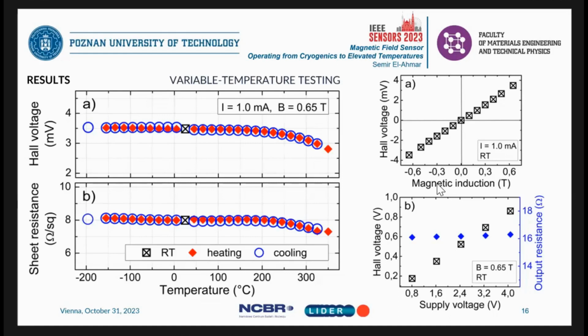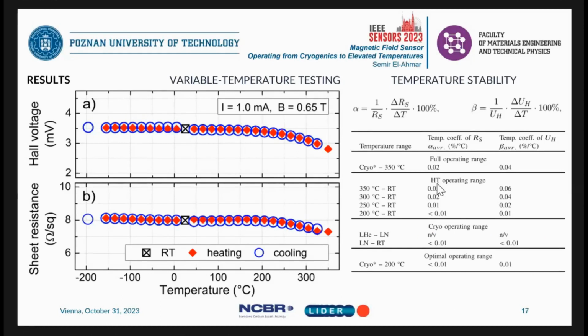And second of all, we can determine and have information about the thermal stability of our sensor, determining the temperature coefficients of these parameters. It was mentioned during the last presentation also. And we can see here that in a full range of operation from liquid nitrogen to 350 Celsius degrees, the average coefficients of both of these parameters are less than 0.05% per Celsius degree, which is quite nice. It means that our sensor is quite stable.